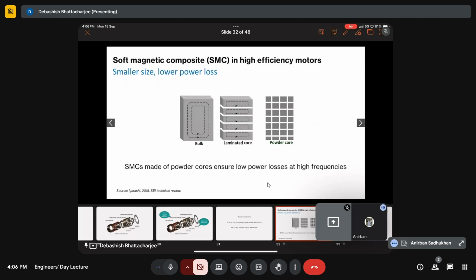Imagine you have powder, iron powder. Iron powder, you can spray dry it, or you can mill it, you can get to 50 microns very easily. That's significantly lower than the 0.27 millimeter that you get.